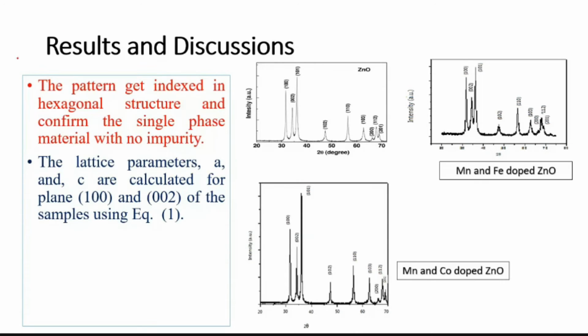Here we can see the results for our samples. This is the zinc oxide sample. When we dope manganese and iron, you will get this pattern. When we dope manganese and cobalt, you will get this pattern. Here you are observing that the peaks are the same for all the materials. So what do we observe here? When we dope manganese and iron, or manganese and cobalt, in zinc oxide, they get fully occupied in the zinc sites.